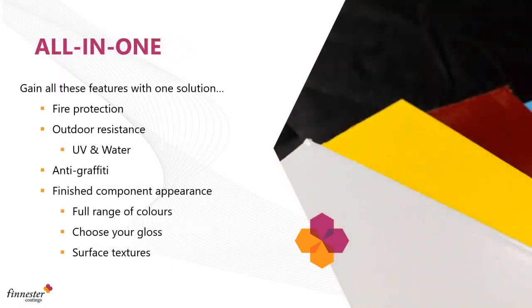It's an all-in-one system. So you get the solution to the fire protection. What we should say is the ceramifying layer, being predominantly inorganic in nature, gives excellent outdoor resistance. So inorganic chemistry will give you very good outdoor resistance, no yellowing, no problems with UV light exposure, and excellent water resistance. And we've done accelerated weathering tests to check this out. It will also give anti-graffiti properties and surface properties that will allow you to clean off graffiti and ensure that those damages are repaired easily.